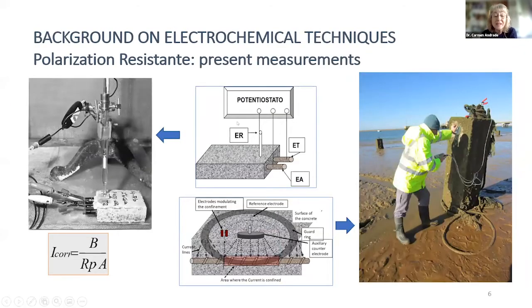After, we extended it to any kind of media, and we also developed a portable corrosion rate meter together with these people I mentioned before. We use a guard ring to confine the current inside a certain area, in order to have very well delimited the area that we are polarizing.